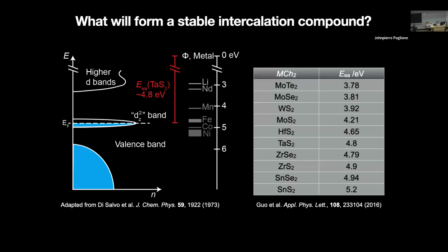And so that at least is a place to start. In my group, we've tried, maybe somebody will find a way to do it. We've tried to put some of these transition metal ions into molybdenum and tungsten, the group 6 chalcogenides. Never work. But with zirconium and hafnium and these other ones, it actually does. And we're sort of trying to work on these other cases as well. Yes? What's your threshold? Oh, like where it stops working? Yeah. For us, below molybdenum sulfide doesn't work so far. But I don't know exactly what that precise threshold is.